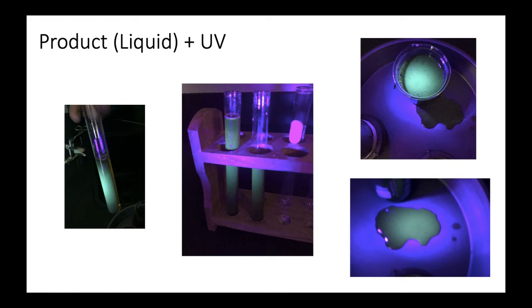I would like to note that because of unreacted orange juice, the solution was most likely tinged green by the quantum dots emitting blue light through that yellow-orangeous liquid. Although I could not eliminate the possibility that the orange juice produced slightly bigger quantum dots than the gelatin did, which would also explain the green photoluminescence.